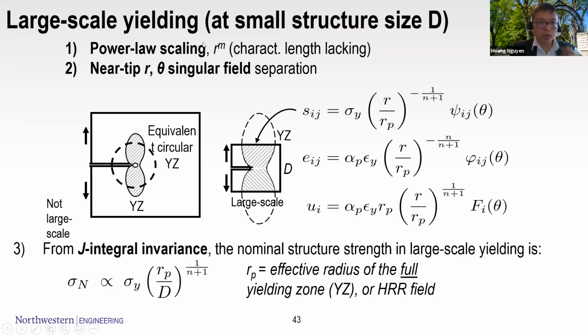So for large-scale yielding, which means that you have a specimen size comparable to the yielding zone, you can come up with some power law of the strain field and the displacement field. You can see that the stress field should follow the power of -1 over n+1. And because of the relation from the Ramberg-Osgood law, the strain follows the power of -n divided by n+1. And then the displacement field is the integral of the strain field here. So hence it follows a power of 1 over n+1.